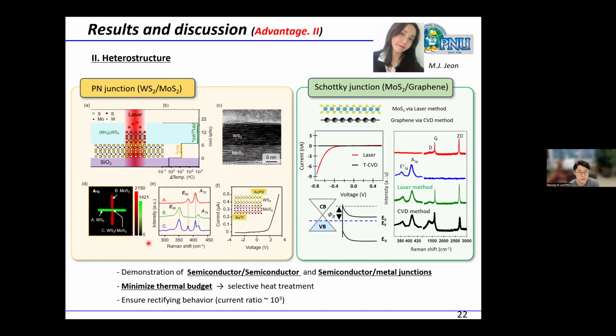Raman mapping confirmed the high quality of both layers and the formation of a well-defined PN junction at the overlapped region. Electrical measurements clearly reveal rectifying behavior, with the forward and reverse current ratio almost 10^3. Using the same approach, we can also demonstrate a MoS2 graphene Schottky junction. In this process, we first form the graphene layer, and then using this laser annealing method, we stack the MoS2 layer directly on the graphene.